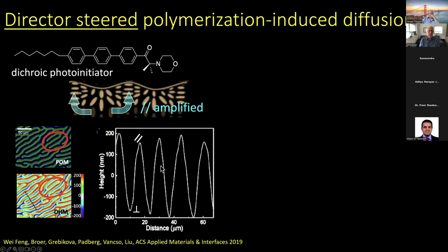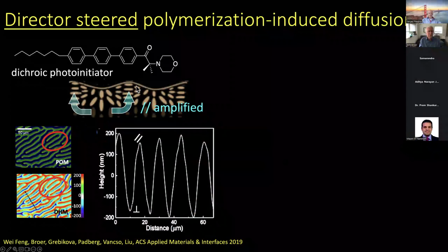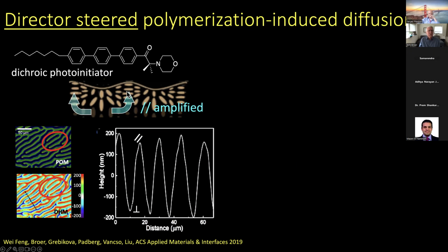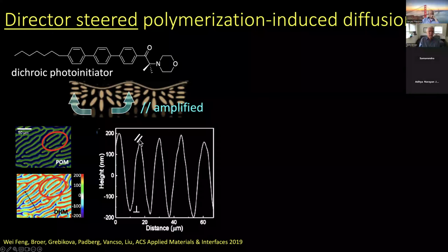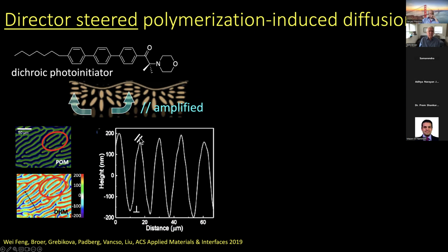So you can imagine that if you have your helix like this, and you are now developing a special photoinitiator, which is dichroic in nature, you might understand that you will have a high absorption in the planar area, where the photoinitiator is also planar. The photoinitiator aligns with the liquid crystal, and you will have a low absorption in the direction perpendicular. Yeah? That means that the polymerization rate in this area is higher, and during this polymerization, a diffusion process is initiated where molecules diffuse from the slow polymerizing areas to the fast polymerizing areas. And that creates a system where, at the end, you create a polymer with a large modulation of the height, with the parallel molecules in the hills and the perpendicular molecules in the valleys of this system.